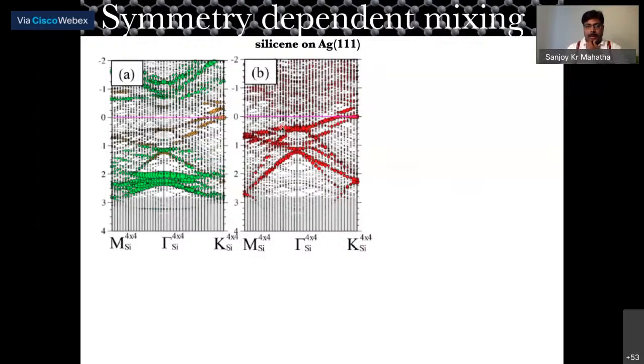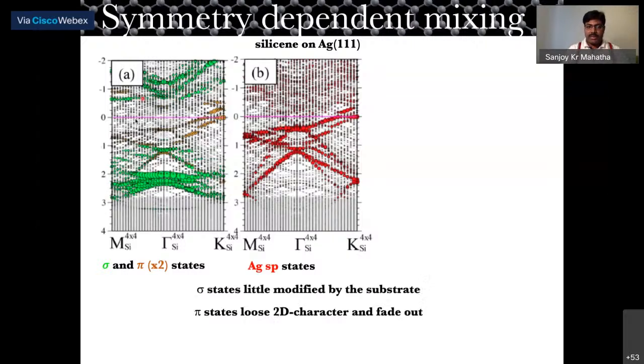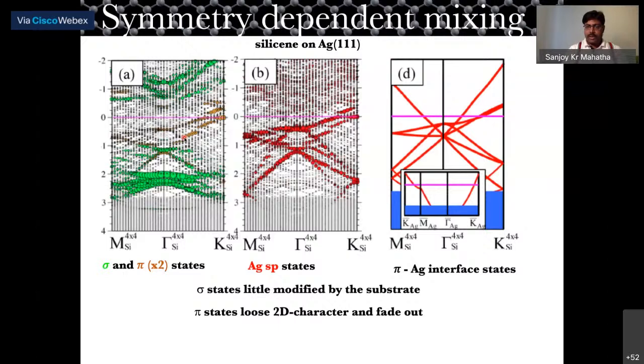Okay, so from here we can say that the sigma states are not really affected by the substrate because there are no silver states here. Okay, but the pi states are strongly affected by the silver 111 because they lie in the same energy, or they have the same kind of dispersion. And what we claim is these pi states lose their two-dimensional character and fade out when we put them on top of silver 111. And this you can easily understand.